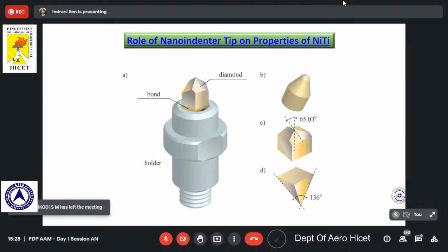Okay, now to figure out the pseudoelasticity, we used a smart way in which we, of course, did nano indentation, but we used two different kinds of indenter tip. In one case, this is the Berkovich indenter tip, popularly known as Berkovich, very commonly used for nano indentation. If you want to use nano indentation, this is the most preferable indenter tip geometry. Okay, it gives a triangular shaped impression once we indent it on a material.